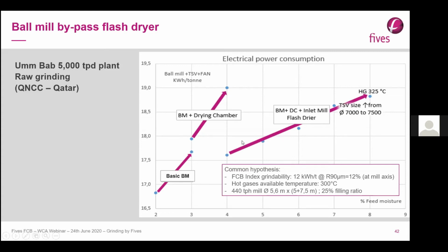This is an overview of all the drying solutions with ball mills, starting from a basic ball mill without any dedicated equipment for the drying. The first step is to add the drying chamber in the shell of the ball mill, and then we install this inlet mill flash dryer that I showed you, and doing so, we are able to dry up to 8% moisture at the mill inlet.